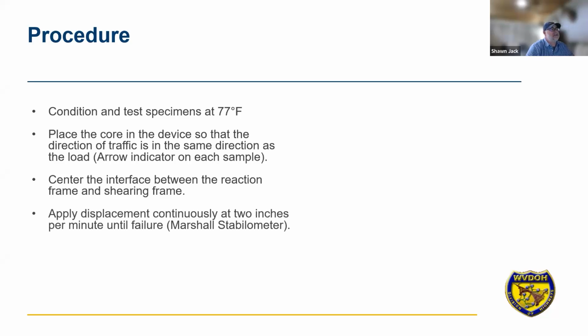And we're going to apply displacement continuously at 2 inches per minute until there's a failure. We use the Marshall stabilometer. Most of the reason we use the Marshall stabilometer is because we already had the equipment in place at the Central Materials and at all of our 10 district laboratories. And so it just made sense.